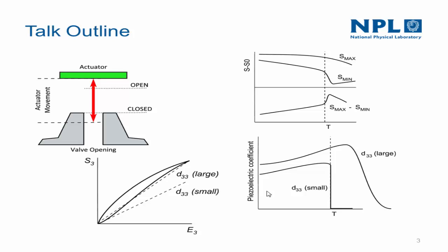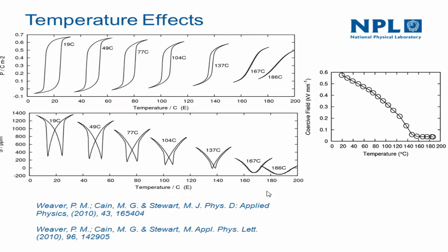So I think we have to be careful, and this is one of the things that we'd like to understand more about, that correlation between the small field and the large field measurements and the influence of electric field on piezoelectric performance at high temperatures. And just out of interest, really, so we can see a little bit of this happening in this. This is a PZT type material with a very low Curie temperature of around 160 degrees.